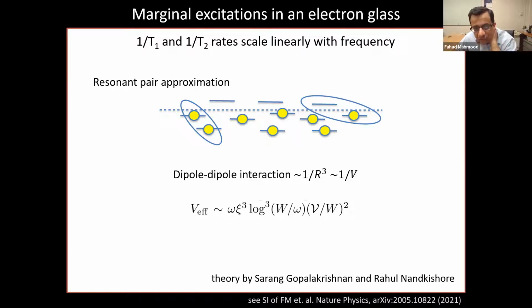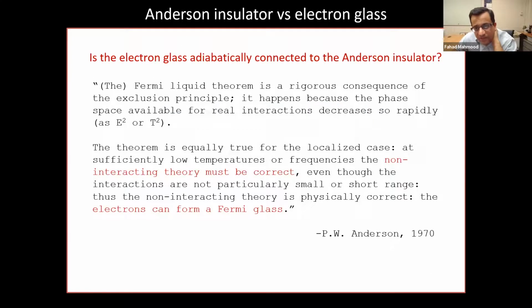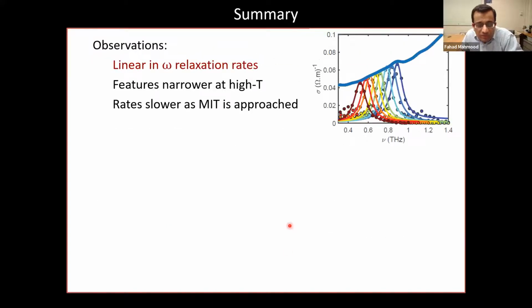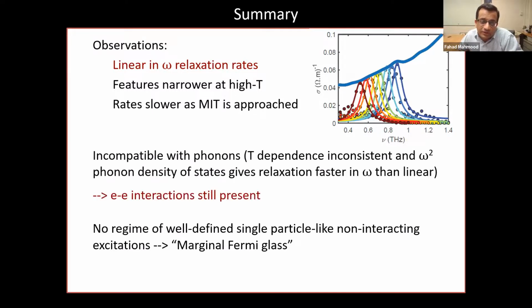Okay, so going back to this question that I had posed earlier, which is: is this Coulomb glass adiabatically connected to an Anderson insulator? What we are finding is that the answer is no, simply because of this linear in frequency relaxation rate we observe, this counterintuitive temperature dependence. It points to the fact that this relaxation is incompatible with phonons, that there are still strong electron-electron interactions present in the system. And so we don't really have a well-defined regime where you can describe the system by non-interacting excitations.